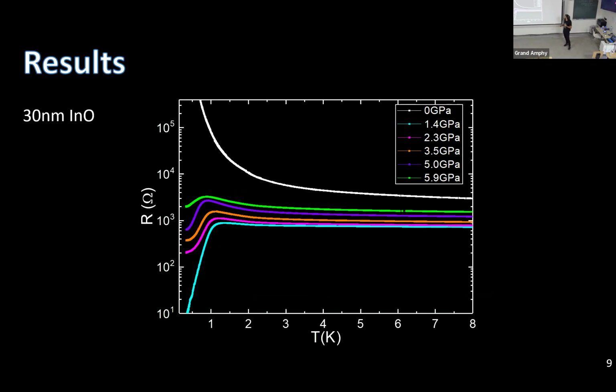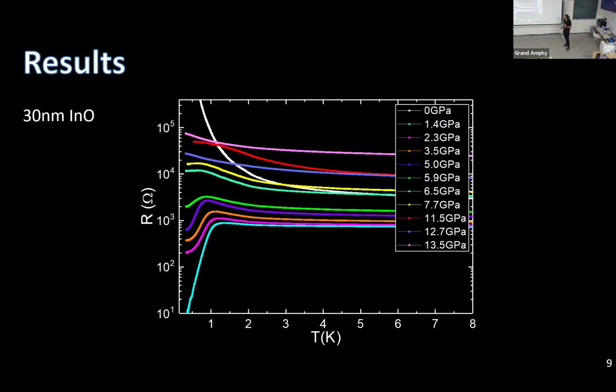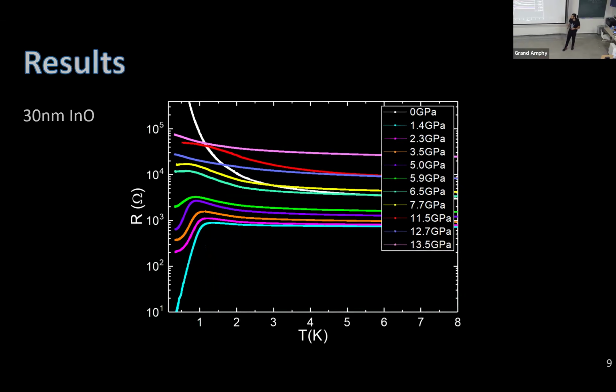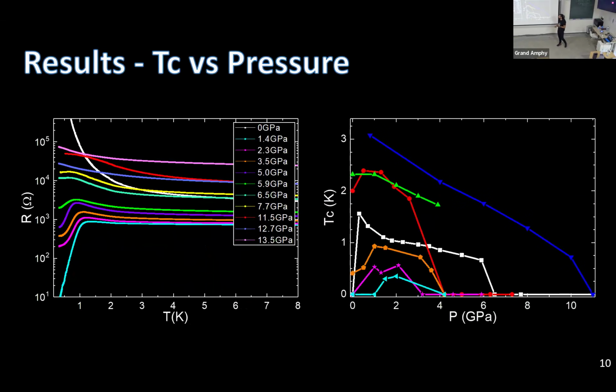The sample goes back to being insulating, the resistance doesn't drop anymore, and we go further into the insulating regime as we continue pressurizing the sample even more. Not just this sample, we took samples across all the SIT, with different starting points and different critical temperatures at ambient pressure. We pressurized all of them, and we see pretty much the same results on all of our indium oxide samples.